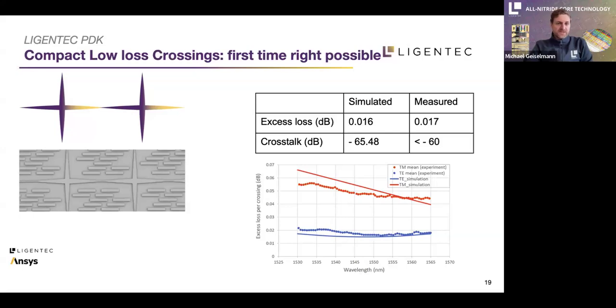Some of our PDK components here, a few highlights. We have a compact low loss crossings that has been shown together with simulations of ANSYS. So a first time fabrication. Here we have a comparison between simulation and measurement of that first time fabricated circuits. We have simulated 0.016 dB of excess loss and measured 0.017 and the crosstalk below minus 60. And so you see in TE and TM simulation and experiment match quite well, which means that we have a quite good understanding of our platform and our PDK, that people can even put their own components and have a first time right possible.